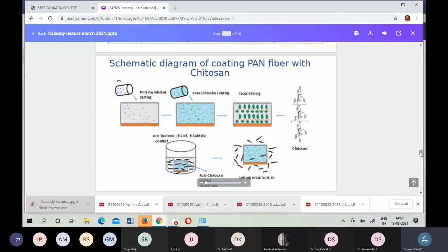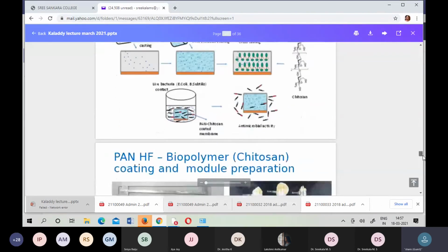So what is the condition? In all 4, the PAN, polyacrylonitrile, is the same, and the solvent we use here is N-methylpyrrolidone. In some cases, in 315B, we use dimethylformamide. The PVP, polyvinyl pyrrolidone, is a pore former, and we use different concentrations of it. The polymer and solvent are more or less the same, only the concentration differs. The PAN concentration in the first one is 12, here also 12. But the PVP concentration I increased from 8 to 10 here. Again here, but here the NMP concentration I reduced. Similarly, in the case of DMF, we use more PVP, like 15 weight percent.